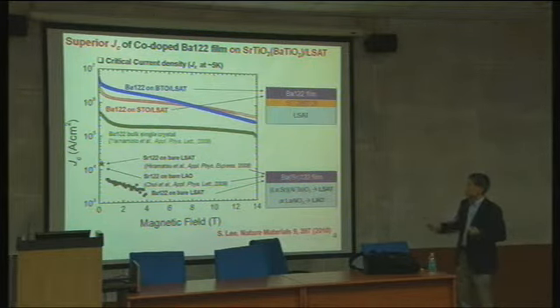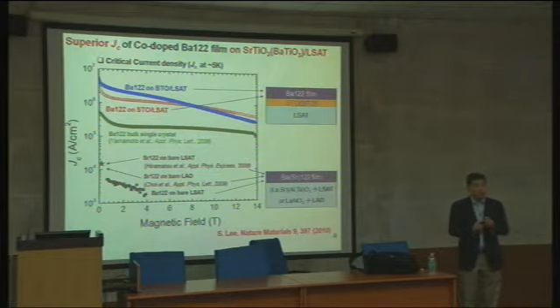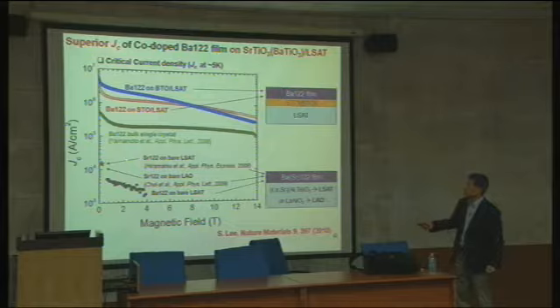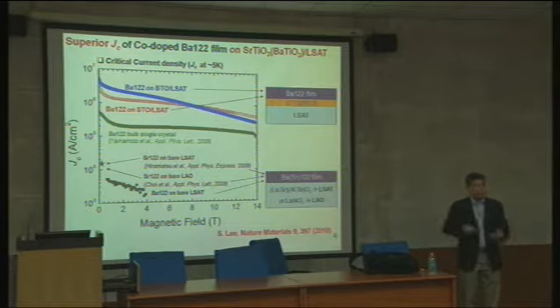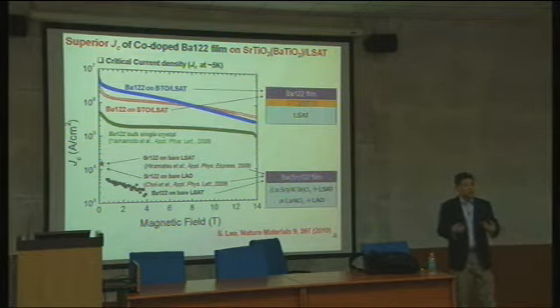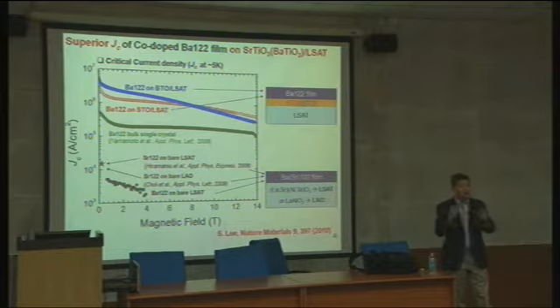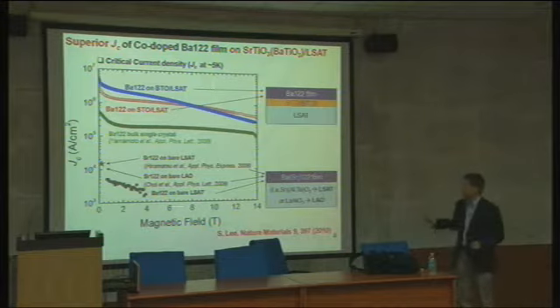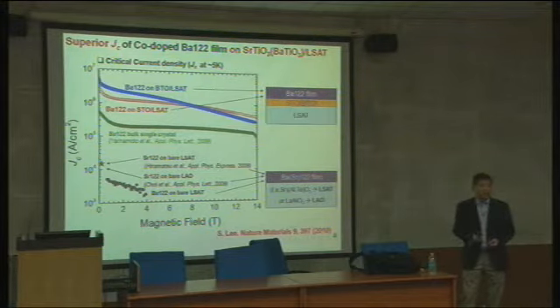But I think this is the one, the pnictide superconductors, and you have this bulk single crystal where the flux pinning is very weak. The bulk single crystal is only 10 to the 5th or 10 to the 6th, but epitaxial thin films can obtain one or two orders of magnitude higher critical current density. This is because we have more flux pinning, like the defects can pin the flux so that a large current can be applied without losing the superconductivity. So that's one of the examples, and we will talk about it later.